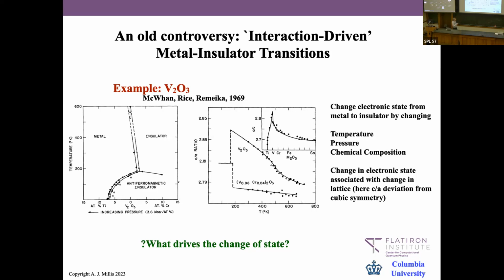Here is the more or less discovery paper from a long time ago. You see this is a material which again has metal and insulator phases, which you can tune between by changing temperature and by changing pressure. Associated with the transition, there's a change in the lattice structure shown here, just as the ratio of the in-plane to the out-of-plane lattice constant.